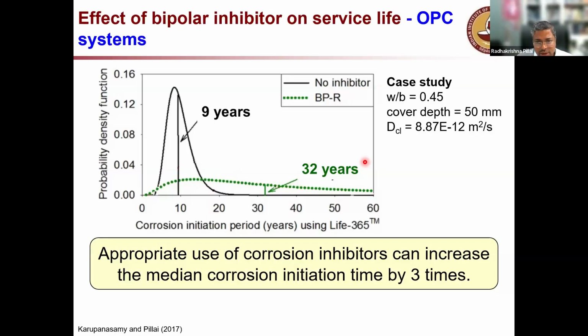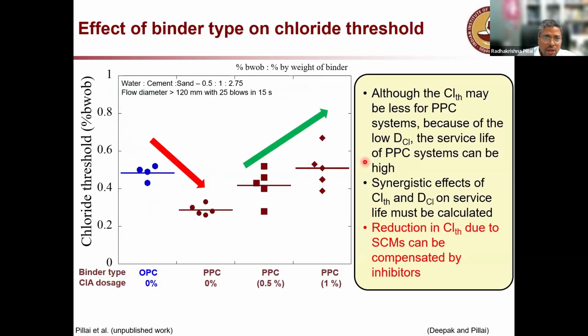So definitely there is a benefit in using corrosion inhibiting admixtures as an integral part. As an admixture means you will mix that with the concrete, and it will help in increasing the chloride threshold of the embedded steel. That means the service life can be increased by 2 to 3 times. So let me skip this particular slide here.